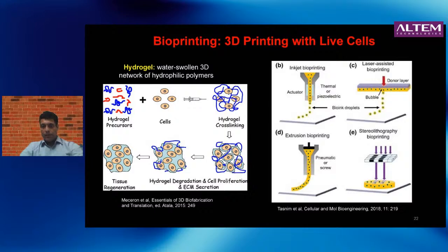One of them is inkjet printing. That is where you have a solution or a gel rather, where you can have cells encapsulated. There's an actuator which works on thermal or piezoelectric effect, so that little drops of what is known as a bioink would come out of this nozzle and get deposited layer by layer. Or you can have the same gel put on a slide where you shine light, and you can again get these drops of gels to get deposited on the surface.